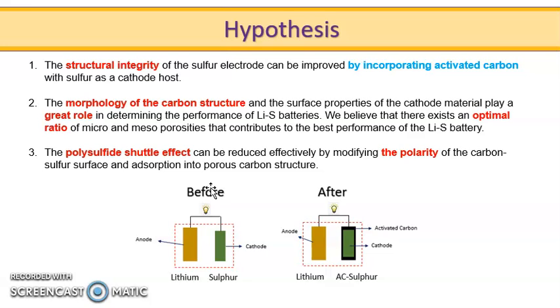So our hypothesis from this study is that the structural integrity of the sulfur cathode can be improved by incorporating activated carbon with sulfur as a cathode host, as you can see in the figure here. The morphology of the carbon structure and the surface properties of the cathode material play a great role in determining the performance of lithium-sulfur batteries. We believe there exists an optimal ratio of micro and meso porosity that contributes to the best performance of lithium-sulfur batteries and traps the highest possible amount of lithium polysulfide. The lithium polysulfide shuttle effect can be reduced effectively by modifying the polarity of the carbon-sulfur surface and adsorption into the porous carbon structure.